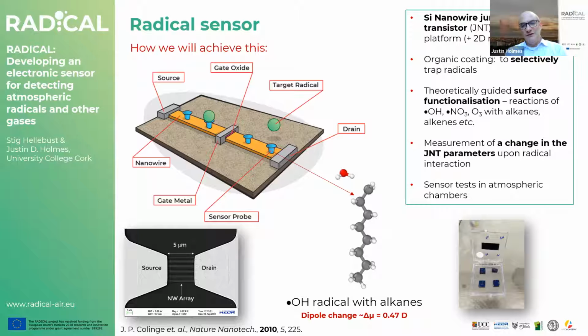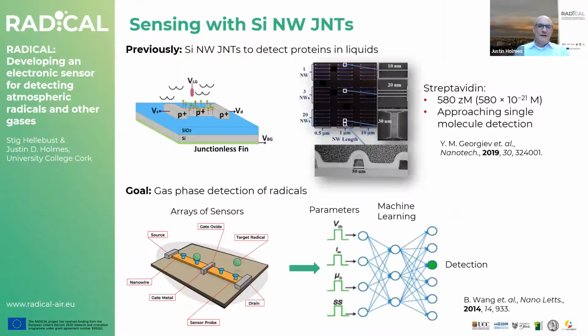And we test these devices in an atmospheric chamber to see what level of sensitivity we have with our devices. Now, this is based on some previous work. Previously we've used these silicon nanowire junctionless transistors to detect proteins in liquids, and this image on the right is a scanning electron microscope image of an array of nanowires, and we're able to detect down to zeptomole concentrations with these devices. But the goal is to transfer our knowledge from this liquid phase into a gas phase and to detect species of radicals, which are often at very low concentrations and very fast reacting. And Stig will come on to talk about the approach for using machine learning to help us with the detection.